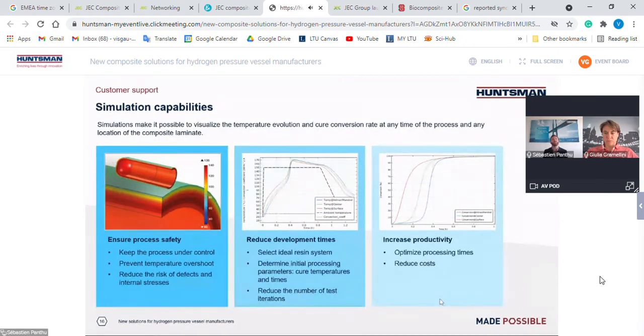So now simulation capability. So we are talking about process simulation, and the objective here is to visualize what's going on during the process at any time and at any location of the composite laminate. So first of all, we can monitor the temperature evolution within the laminate. So this is very important to prevent temperature overshoot, which are due to the exothermic behavior of the epoxy resins. Especially when we want to go for fast cure, we can generate uncontrolled temperature overshoot very high, above 200 Celsius. So it's important to keep everything under control, because otherwise you have a risk of creating some defects in your laminates or generate internal stresses that will go for cracks.